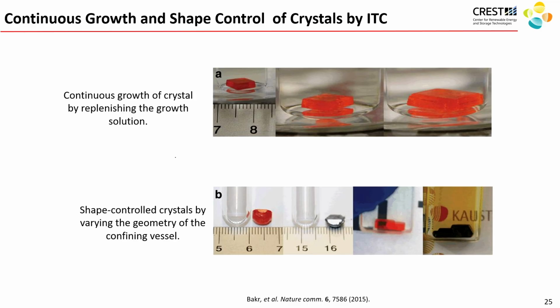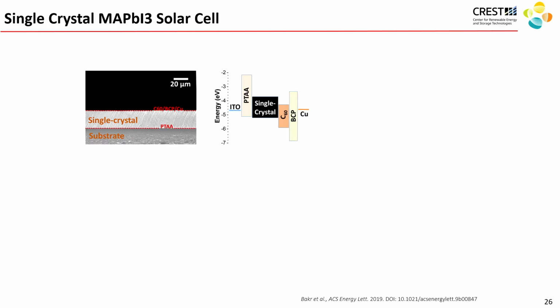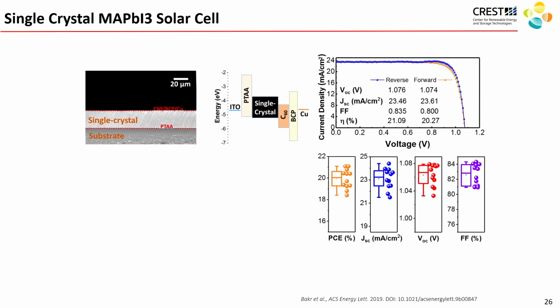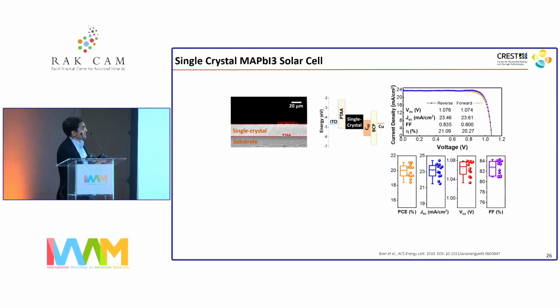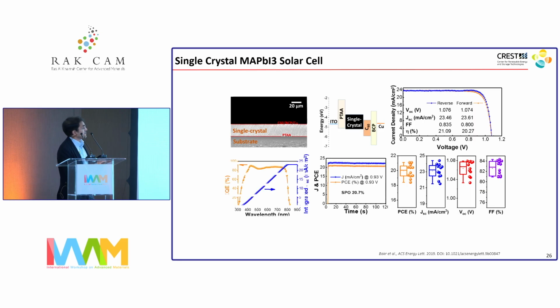And that's very important, because then you could start putting the crystals between two different layers, an electron transport layer and a hole transport layer, and make a single crystal device. What surprised us is typical perovskite films were a few hundred nanometers, but we grew crystals that were 100 times that thick, and we still obtained very efficient devices. And this got us to think,